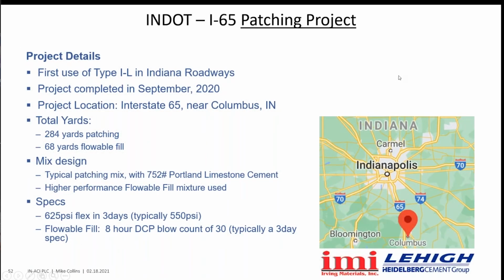Talked about this again briefly in December, but it's worth mentioning again. We did an I-65 patching project where Lehigh worked with IMI on this project back in September. And so this was on Interstate 65 near Columbus, about 284 yards of patching and 68 yards of flowable fill. There was nothing unusual in this mix, pretty typical patching mix, had 752 pounds of Portland limestone cement. It was a higher performance flowable fill that was used.